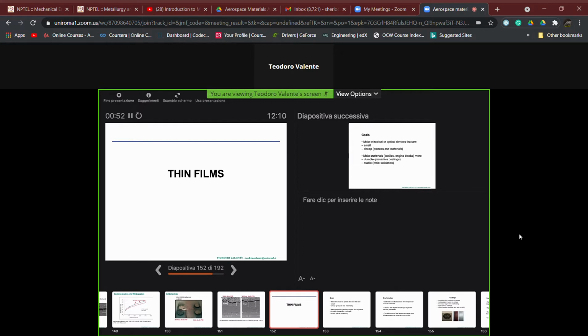and thus also due to very low deposition rates which characterize this set of techniques under the thin film technologies, we do have, on average, maximum coating thickness which is around some micrometers. We can go very down in the thickness up to hundreds of nanometers,